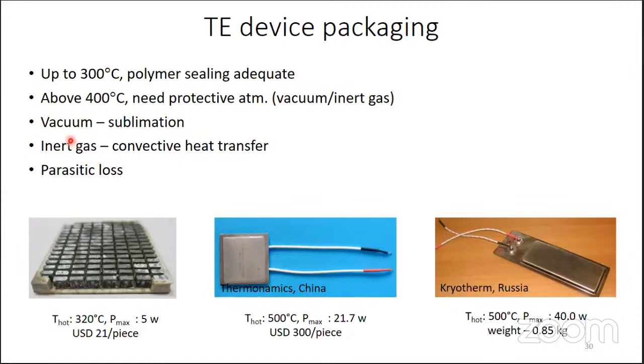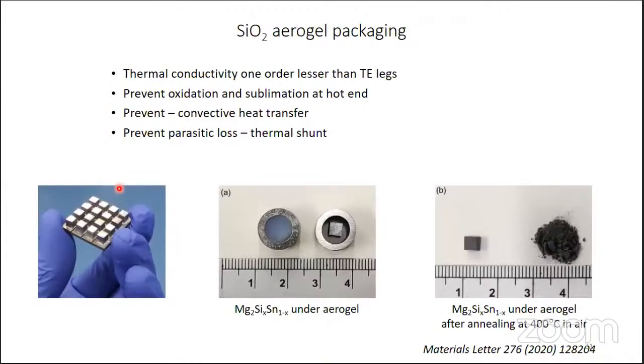And inside, you can put either some inert gas or vacuum. But if you put vacuum, a sublimation problem is there in most of the materials. And if you put inert gas, you will have thermal shunt. It means the gas is there, so there will be convective heat loss, parasitic losses. So what we came up with is a kind of solution. Of course, this is already known, but not for this kind of device.